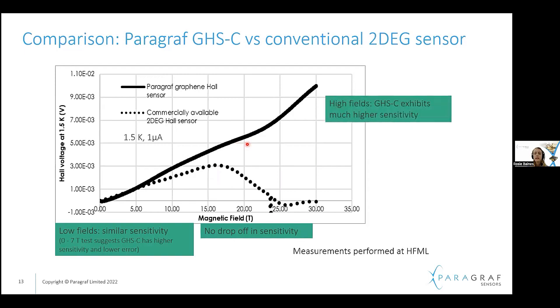Then at those really high fields, we're seeing a much bigger drop off in the properties of the commercially available sensor, and we're seeing non-unique Hall voltage results here. This is a nice comparison over the full 30 Tesla range that was done at HFML. And the power dissipation at this highest field is only 10 picowatts, so very, very low power.